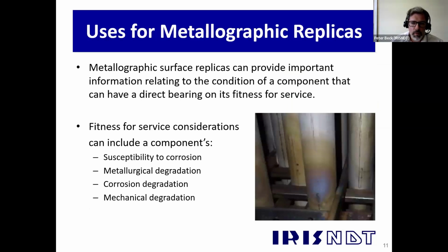So this is one of the uses we've had recently on replication. So we had these boiler tubes that had a heat tint on, so they're a stainless steel. Obviously this heat tint indicates they've probably been up between 500-600 degrees. So the customer's concerned whether there was any degradation, whether they may be sensitized. So sensitization is carbides forming at grain boundaries, essentially. Potentially you could also get sigma phase forming at these temperatures, but it's probably on the low side for it.